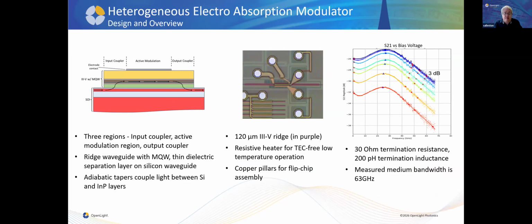So this is the starting point. Here at OpenLight, we have a PDK. We've been working for many years with a number of customers. And as part of that, we've introduced an electro-absorption modulator. We really like electro-absorption modulators for datacom applications for a couple of reasons. Primarily, they're small. The device length, which you can see in the middle micrograph in purple, the modulator itself, is only about 120 microns long.